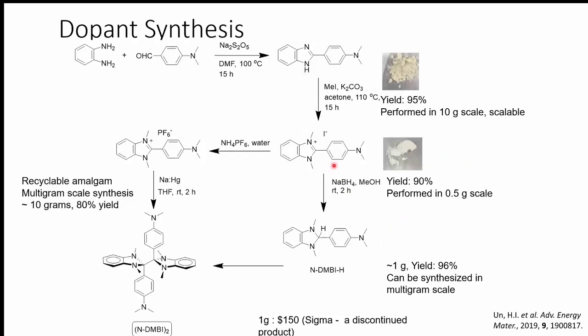Now, as for the dopant, how do we synthesize it? We basically just take our amine and aldehyde. We do a condensation using an oxidizing agent to get our imidazole. And we can do that on a 10 gram scale. It has a very high yield. Then we alkylate it to put methyl groups over here. So this iodide compound has very low solubility. So if we want to make the H compound, we just use sodium borohydride and we get the H compound in multiple grams.